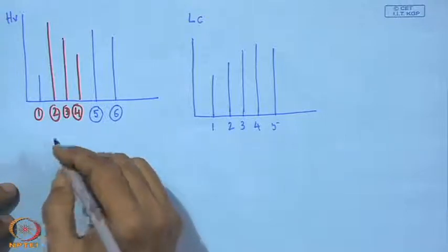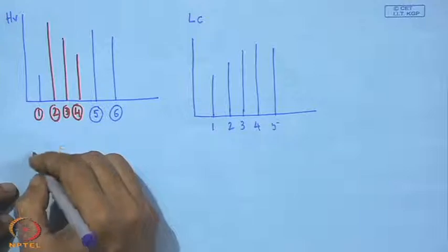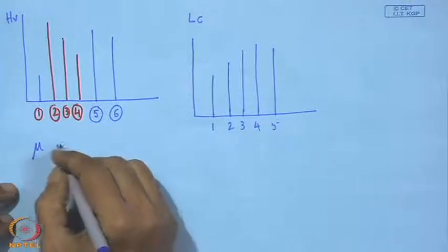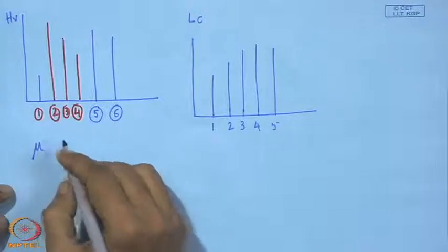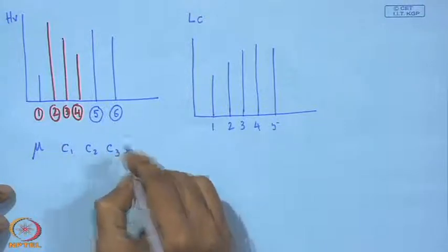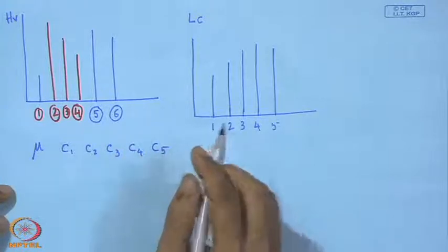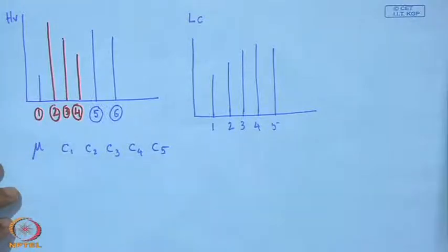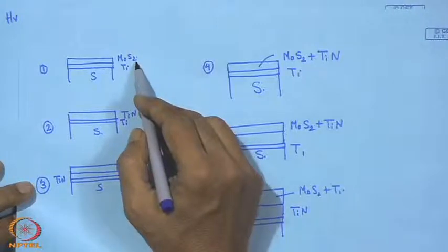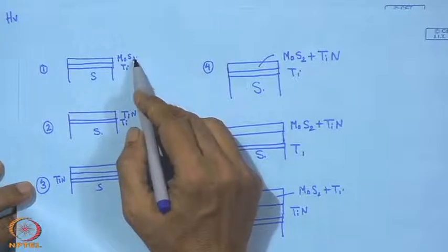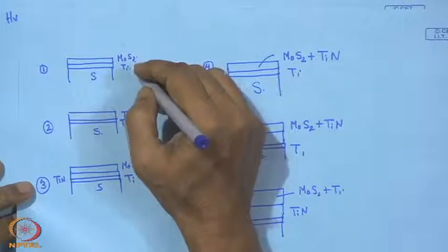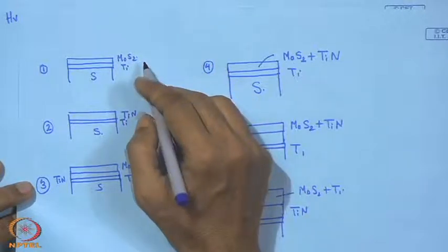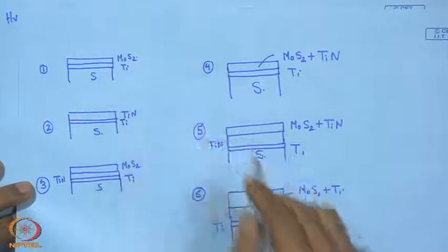Now, what is important is the coefficient of friction. This is the coefficient of friction one can find out in the ball-on-disc test, that means it is a tribometer, with the pin on disc, and this is also our observation for these samples, C1, C2, C3, C4 and C5. Now, here obviously, since one is having just pure MoS2, from the standpoint of lubricity, that is going to be the best one. However, that is short lived, that means the life of this coating is very short, it is a short lived coating.